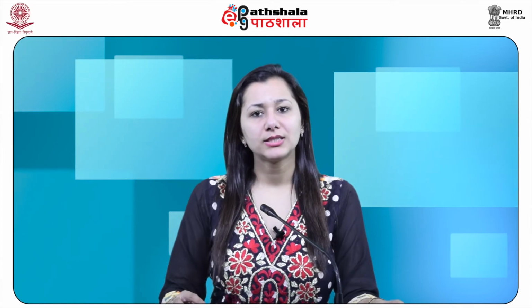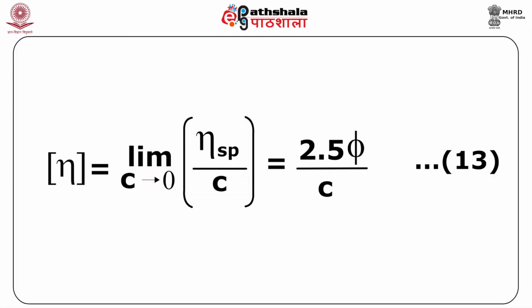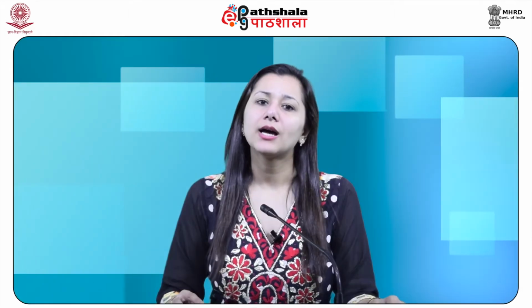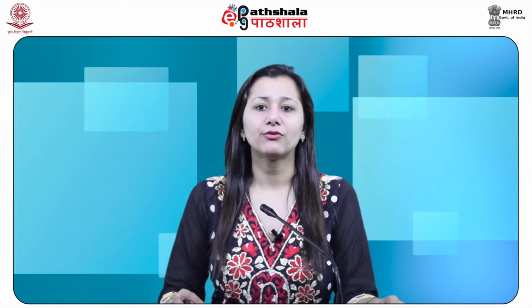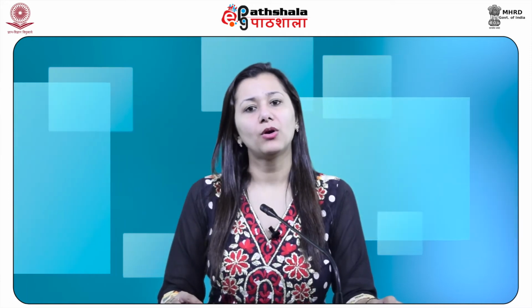Hence, from equations 10 and 12, we get the intrinsic viscosity eta equals the limit of eta sp by c as c tends to 0, equals 2.5 phi by c, as shown in equation 13. It is, however, very difficult to measure phi, the volume fraction of the polymer molecules in solution.